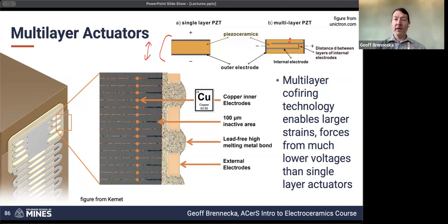So each layer gives me the same piezoelectric response, but now I can add that up in series, and so I end up with the same amount of strain as I got with that one, but at a lower overall voltage because I split that voltage across a bunch of thinner layers to give me the same field. Now, this version is going to require higher current to operate, but in many cases that's perfectly acceptable. So I just wanted to use this as an example to show that everything that we just talked about from a multi-layer ceramic capacitor perspective is very much applicable, even if you're not actually interested in trying to compete with the capacitor manufacturers and make MLCCs. A lot of the tools of the trade and tricks that they've developed, we can apply to a bunch of other materials and devices as well.